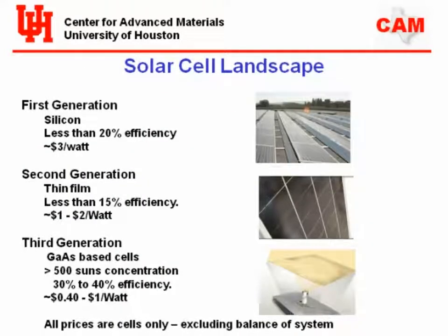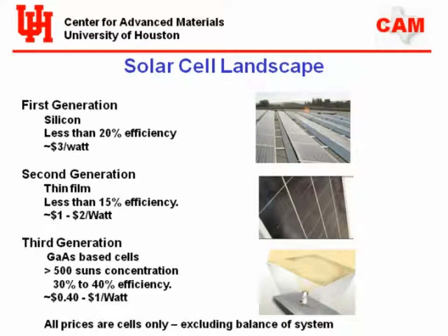In terms of current technology, the first generation for the past 60 years is silicon. Silicon panels have increased in efficiency — champion cells are at the 19–20% level, commercial ones still at 16–17% maximum, and they cost about three dollars a watt. A second generation in the last five years is thin film cells — cadmium telluride, copper indium selenide — less than 15% efficiency, around a couple dollars a watt, but lower efficiency means you need more area.